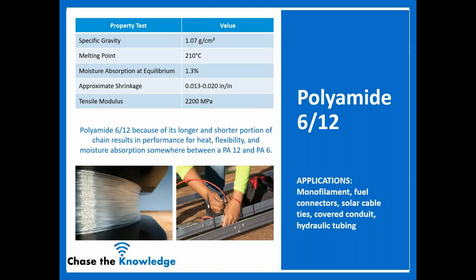Okay. Now we'll talk about 612 briefly. So you'll notice our tensile modulus has increased a little bit. So 612 and 610, which we'll talk about next, because it has a longer and shorter portion of its chain, you're going to get heat performance, flexibility, and moisture absorption that kind of falls somewhere between the two because you have kind of a piece of both of them. And so you're going to get performance in between them. Our tensile modulus was 1400 for the 12. It's 2200 for the 612. So it's gone up because it's getting closer and less flexible, more like a short chain. Again, kind of falling in between.